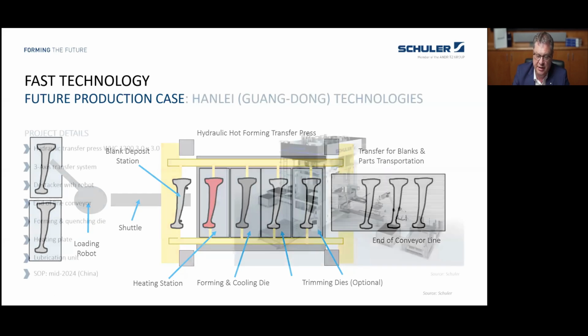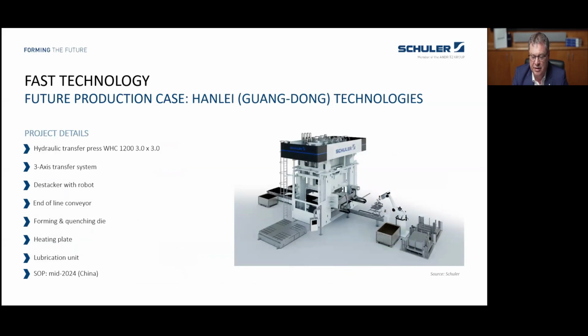So, and this is the next picture. This is how it looks like. It's a hydraulic 1200 ton press with 3 by 3 meter bolster size, classical destacker with the shuttle and the triax transfer mounted to the press. We have 2 moving bolsters for fast die change. And at the end of the press, there is a conveyor and then 2 boxes for unloading the part. So a classical transfer press design, nothing very special.